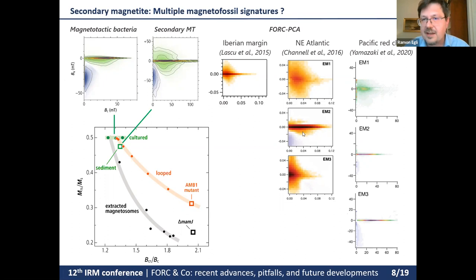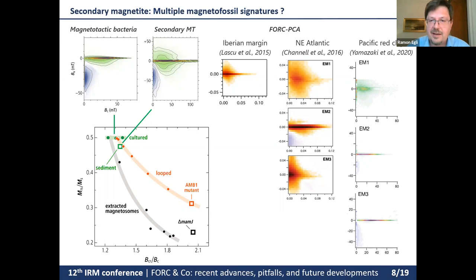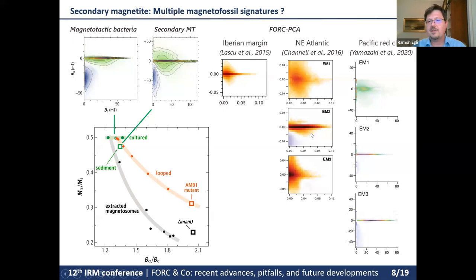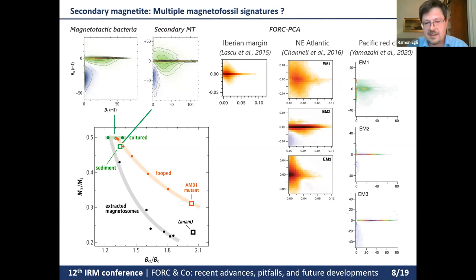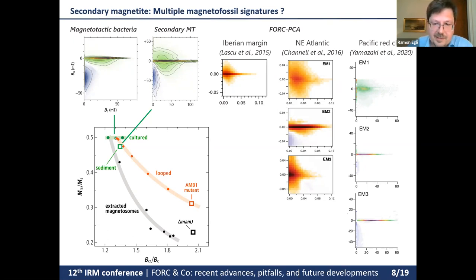This is possible because if the relative abundance of single-stranded chains versus multi-stranded chains is changing down core, then PCA reproduces this change by dividing the magnetofossil signature into two end members — a natural consequence of PCA mathematics. What we are seeing here is a very interesting environmental signal: the ratio between single-chain-producing bacteria and multi-stranded-chain-producing bacteria. These two types of bacteria occupy different ecological niches, and there must be a hidden reason for these changes which we will discover in the future.